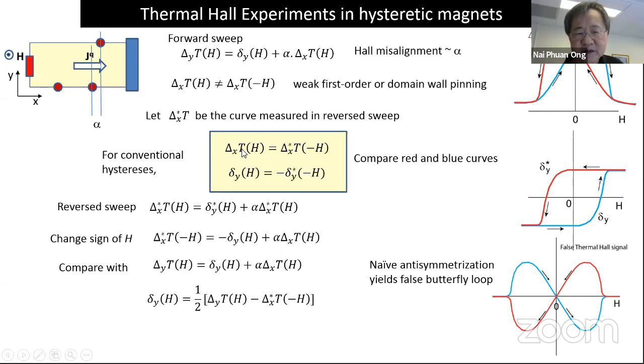And then if you impose the symmetry that I mentioned in the yellow box, you can write this in terms of what you get in the forward sweep, right? So now you have this equation. And now if I repeat the forward sweep equation at the very first line down here, you notice that these two terms now are identical, and these two terms are also identical. So it remains to add and subtract them. In particular, if you desire the intrinsic Hall signal, you get it as the difference of these two curves. So this is Max's technique. In our lab, we call this the in-in-out-out technique. But this, I think, is a clearer way to explain it, right? This is not the naive.